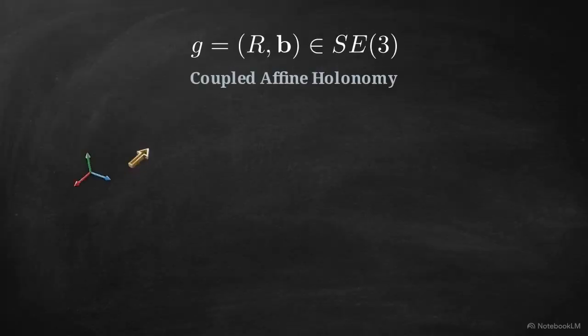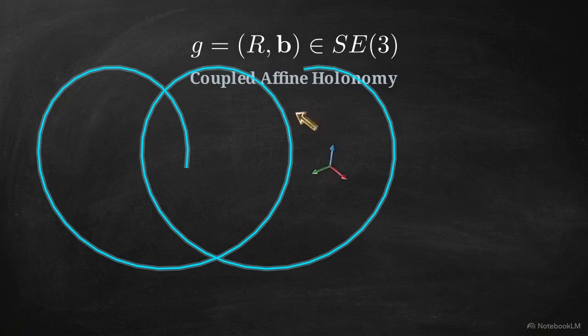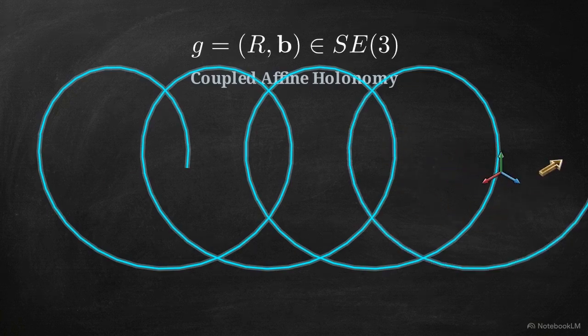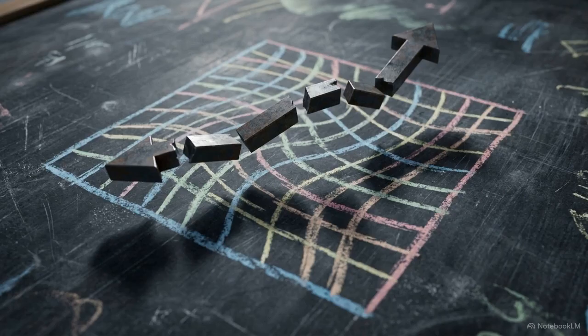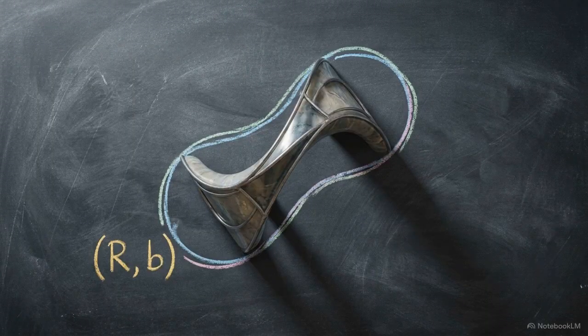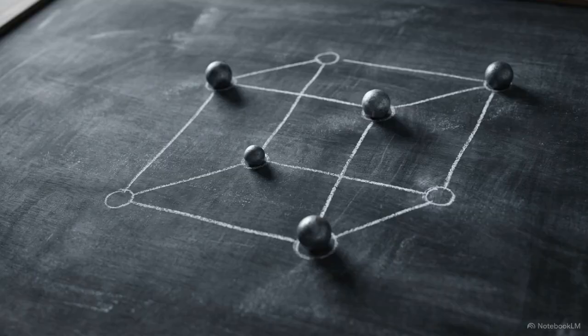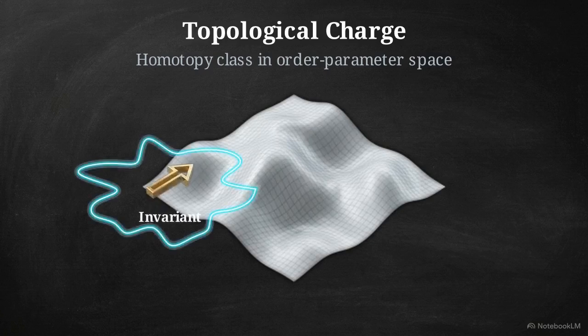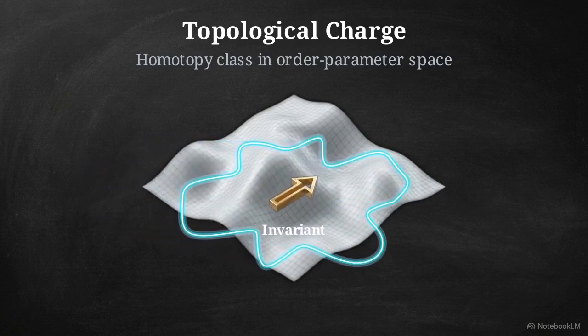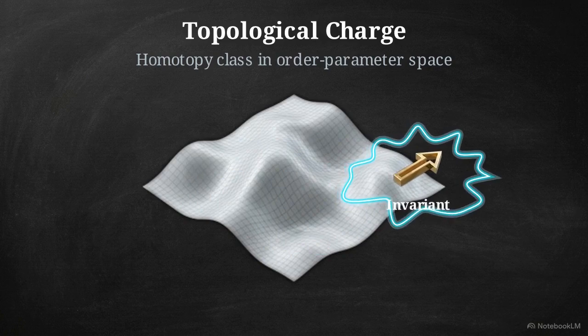It must be calculated as a combined element of the Euclidean group, coupling rotation and translation together. Standard vector addition is a specialized local approximation. In a coupled dislocation-disclination system, it fails entirely. Global accuracy requires calculating the full affine holonomy. Defining the vector as a geometric gap naturally leads to the topological classification of ordered media. Topology strips away the physical energetics of the defect and redefines the Burgers vector strictly as a topological charge, corresponding to free homotopy classes of loops within the crystal's order parameter space.